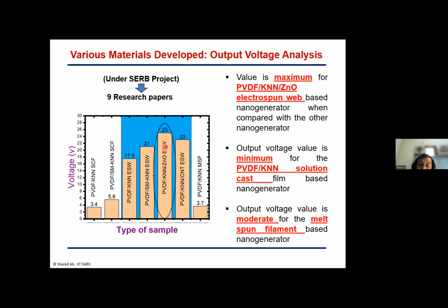So we have optimized the different kinds of combination, different kinds of process and all, and of course, melt spinning as well. So melt spinning along with KNN and PVDF is getting only 3 to 4 volt. Of course, this particular material is not poled, but obviously if we apply high voltage over here after filament formation, then definitely this voltage is going to improve, right? So at the moment, in situ poling, we are taking help in the electrospinning process, and we can see that we can harvest up to 25 volt from the structure, from the material itself, that nothing is there on the material. So we are not dependent on the sun, we are not dependent on the wind.